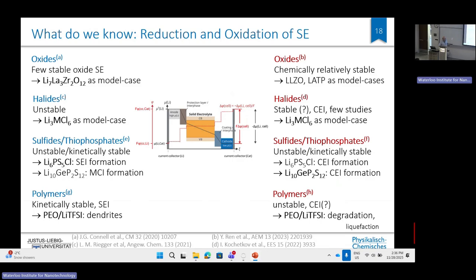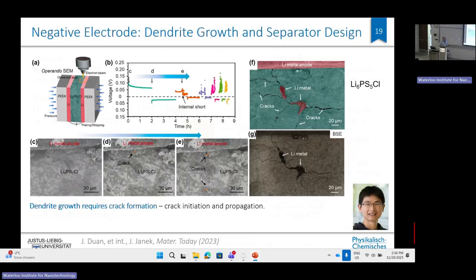On the cathode side, I will not comment so much on that. The halides may have a major advantage because particularly the chlorides may be stable at the high potentials of the cathode, whereas all the sulfides are not stable because the sulfur is easily being oxidized already at 2.5 volt versus lithium, so they need to be protected. So that means the best electrolytes we have with respect to conductivity are the worst when it comes to stability. And this is, of course, something we really have to take care of. That's why I said design of interfaces. We have to design interfaces such that they survive.